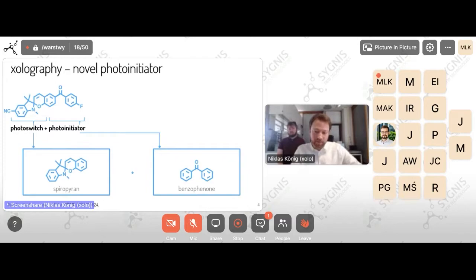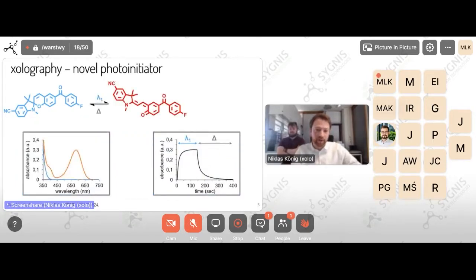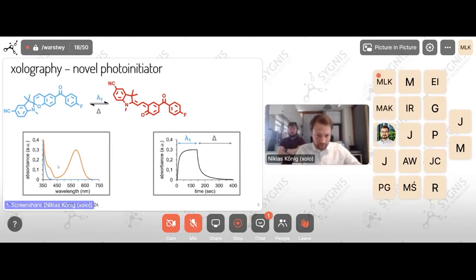But to this benzophenone motif, we incorporated a photo switch. And this is this part here. It's a spiropyran. And spiropyran photo switches are known to go into an open form when they absorb light. Here you see on the left-hand side, in this absorption spectrum, in blue, we have the absorption of the spiropyran closed photoinitiator, and it tails out at around 400 nanometers here.